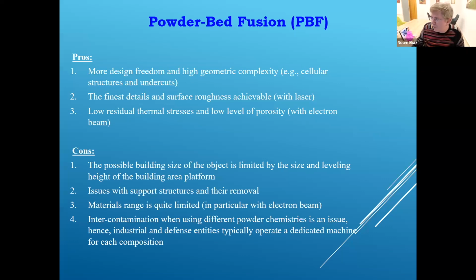Considering the pros and cons of the powder bed fusion process, you have more design freedom and high geometric complexity. For instance, you can print cellular structures and undercuts. You can get the finest details and surface roughness achievable with laser, compared to electron beam, since you can do the powder bed fusion either with laser or with electron beam. When you use electron beam, you do it in vacuum. So with laser, where we also use finer powders, you can get finer surface roughness compared to the powder bed fusion with electron beam. On the other hand, you get low residual stresses and a low level of porosity when you use the electron beam in vacuum.